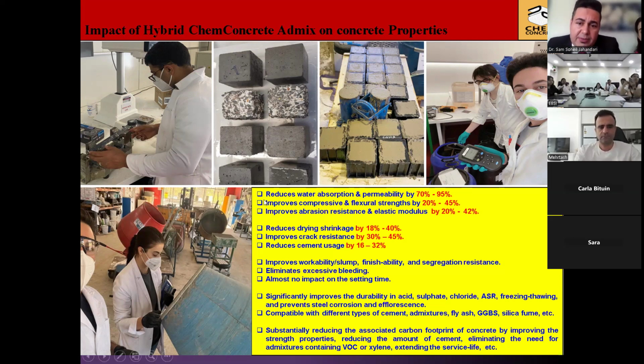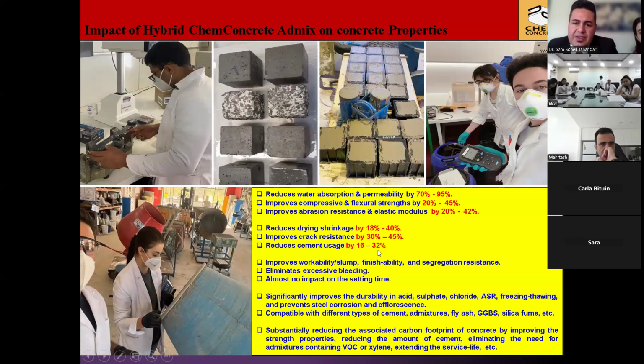So to summarize the main independent test results, it's been proven that our product can reduce the water absorption permeability of concrete by 70 to 95%. It improves compressive and flexural strengths by 20 to 45%, improves abrasion resistance and elastic modulus by 20 to 42%. In terms of compressive strength, sometimes we have achieved even up to 55% as well. It reduces drying shrinkage by 18 to 40%, improves crack resistance by 30 to 45%, reduces cement usage by 16 to 32%. It all depends on the dosage of the admixture used.